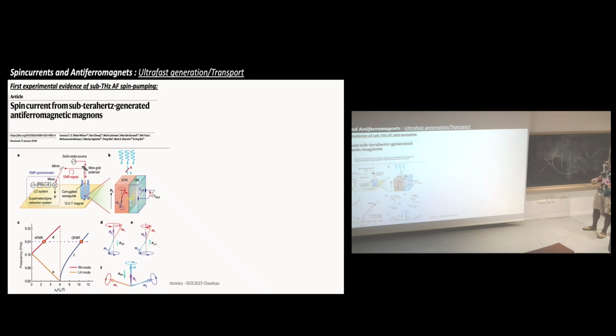So this time, it's an easy axis antiferromagnet. They have shone on the sample electromagnetic waves at 240 gigahertz. And then they look at it as a function of field. Because as I said at the beginning, here you have the two degenerate modes, circularly left and circularly right. But as you increase the field, you have one mode which rises, one mode which decays here. And then basically, if you are at 240, you think that you will cross the resonance at that field typically, okay?